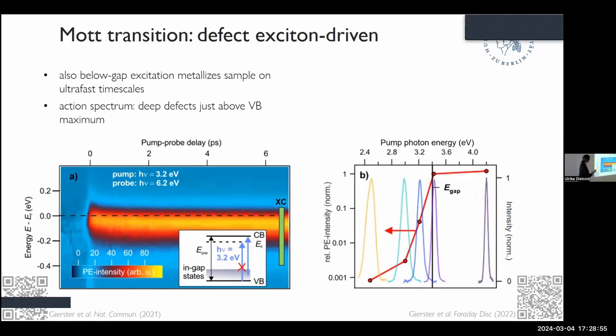You can plot this in an action spectrum here. So this is the photon energy and the intensity of the metallic feature. And you see that you really need sort of high photon energy, so you cannot do this with 800 nanometers. But it's enough to do it with a photon energy below the band gap.